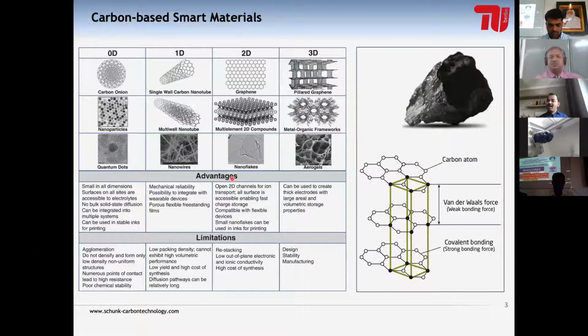These materials have many advantages. As I already mentioned, they are lightweight, their density is very low, they are porous, and they can be used for multiple applications. But these materials have some limitations as well, because when it comes to zero-dimensional material, we always see the agglomeration of these materials. When it comes to the carbon nanotube, these materials generally show low packing density, which generally hampers the applications of these materials.